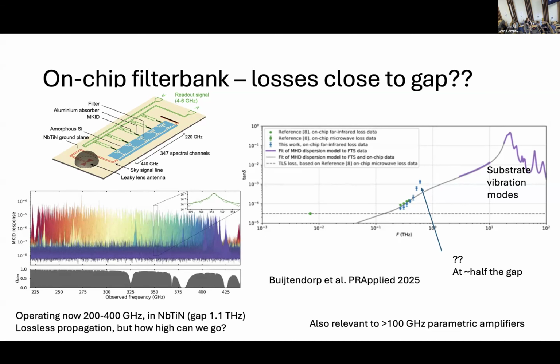So the blue dots here are actually this niobium titanium nitride material. It's a microstrip which is based on amorphous silicon, which can also be another material, but it's the dielectric that we use. And what you see here is FTS data where they try to measure the absorption at higher wavelengths of this dielectric, and you extrapolate what the dielectric loss would be at these somewhat lower frequencies compared to where the real molecular absorption starts to kick in of this dielectric. So all this analysis points, to cut a long story short, to the fact that this part of what we measure is indeed due to substrate mode absorption, so it's not very interesting.